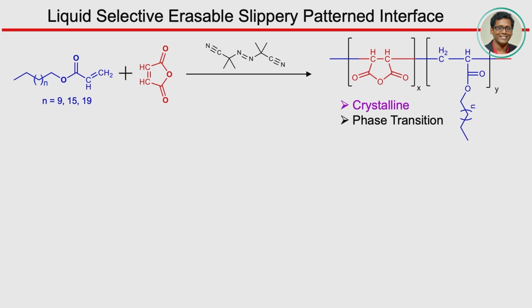So what we thought was to come up with a polymer which is crystalline in nature because of the hexagonal packing of the hydrocarbon tail, depending on the length of the hydrocarbon. If it is something like 15, 18, or 22, it can nicely go into hexagonal packing. You get the crystalline domain, and it also undergoes phase transition. At an elevated temperature, around 50 degrees, the crystalline domain gets disturbed and it undergoes a molten state, and when it comes again below that phase transition temperature, it solidifies. So this is one of the components which is helpful for the phase transitions and crystalline network, and which will contribute to this slippery property against a wide range of liquids.